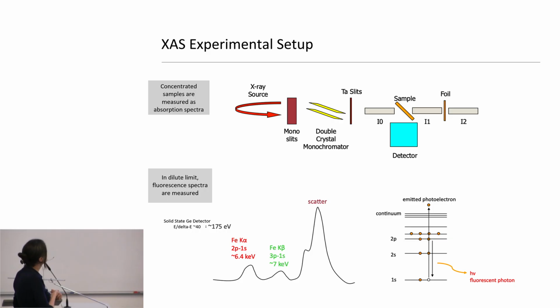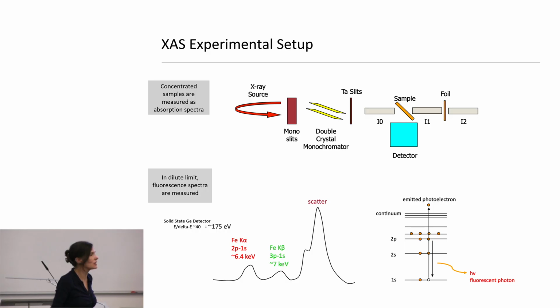It's not real. But what you would see on the detector itself are scattering-based features. So we have both elastic and inelastic features. For something like iron, these detectors will typically have a resolution of about 175 electron volts. So you see big blobs that correspond to a 2p to 1s de-excitation, that 1s core hole being filled by a nearby 2p electron. Those happen at about 6.4 keV for iron. And then about an order of magnitude lower in probability is the 3p to 1s. But what you can see is that it's relatively featureless. In fact, in many detectors, as they age, even the K-alpha and K-beta are kind of overlapping. So you just set a window near the iron and hope to hit it, right?